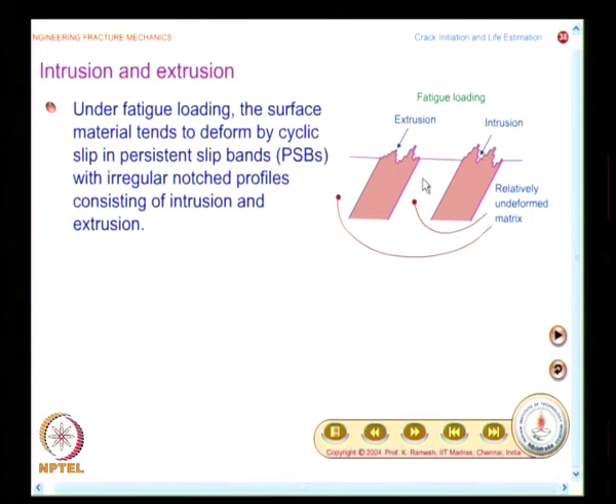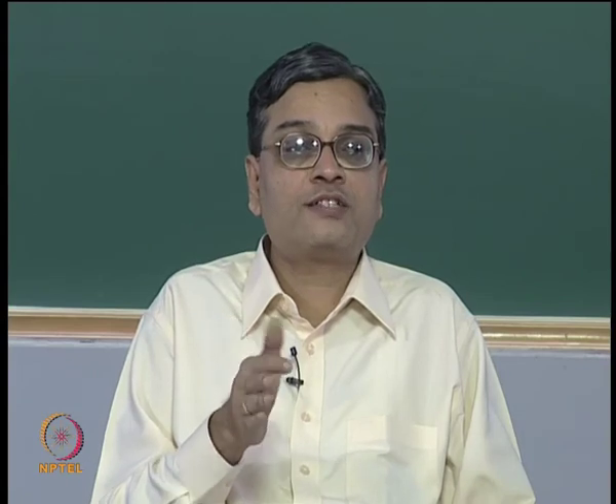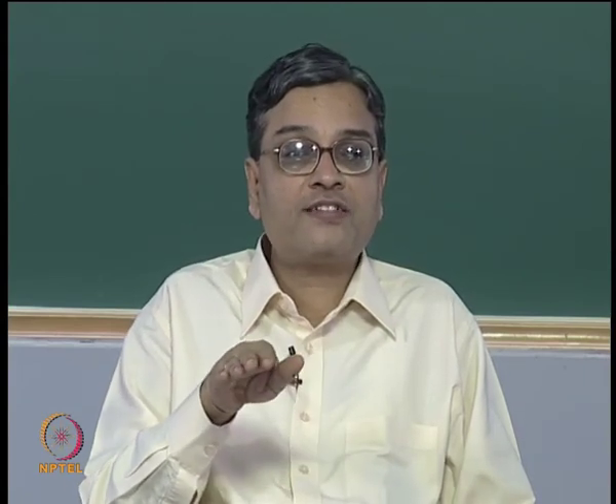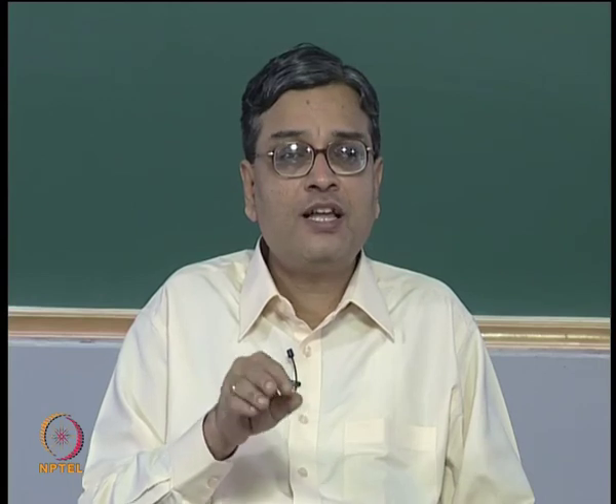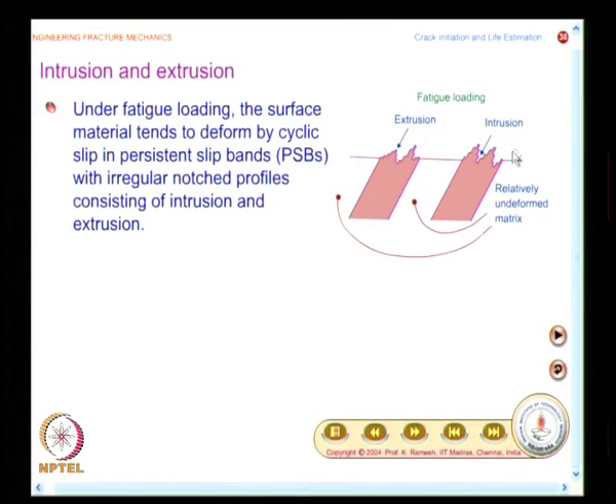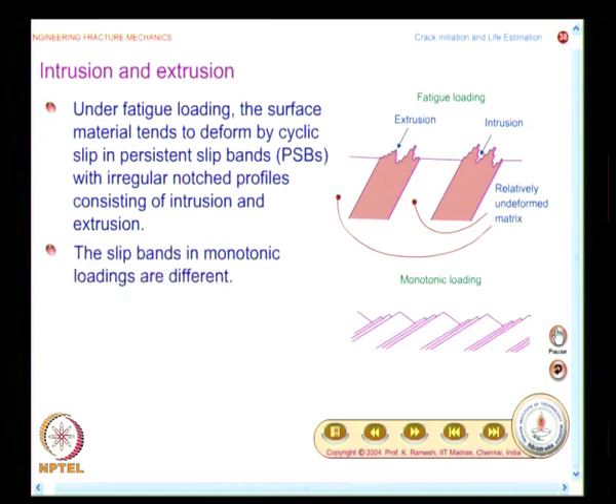So, that means when you have a fatigue loading, what this slide shows is that a smoothly polished fatigue surface would become rough because of intrusion and extrusion, which happens at a very, very small scale. It is very highly magnified for clarity. So, the roughness of the surface should change, which we would see by an experiment. And what you find is that the type of intrusion and extrusion you see here is different when you have fatigue loading and when you have monotonic loading. That is also recorded in the literature. That is what is shown here.